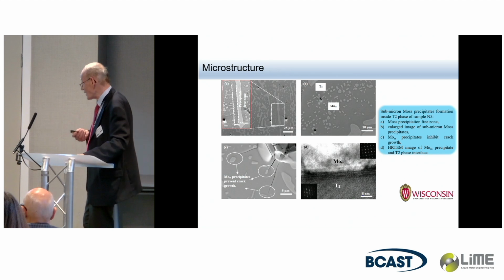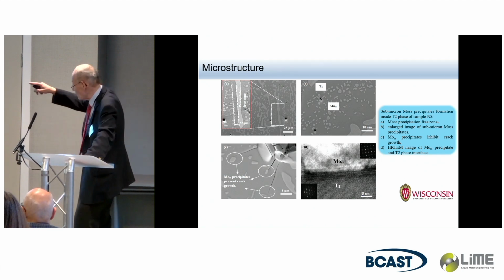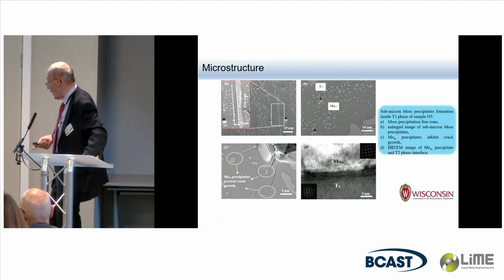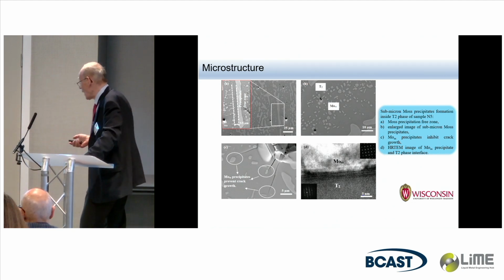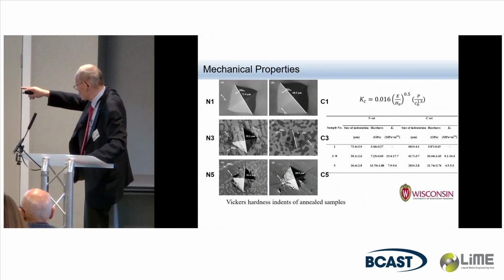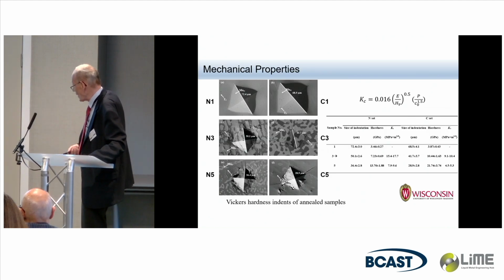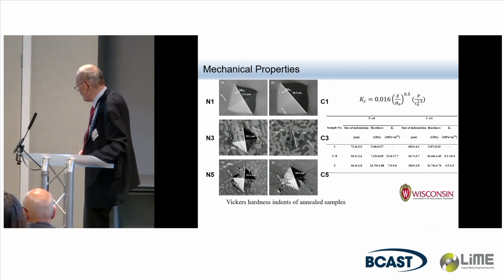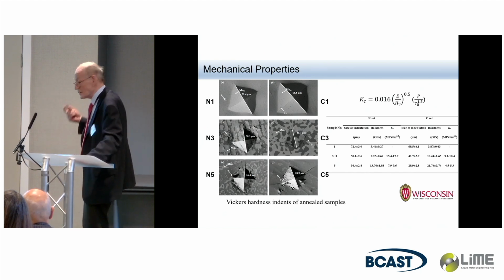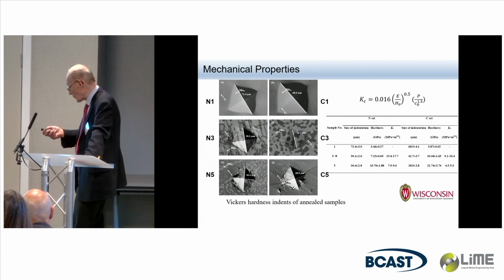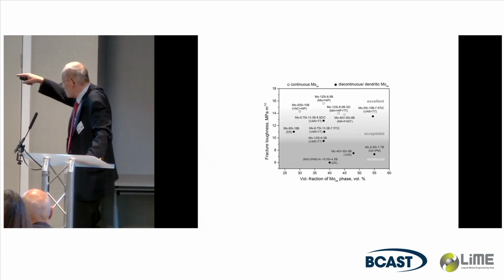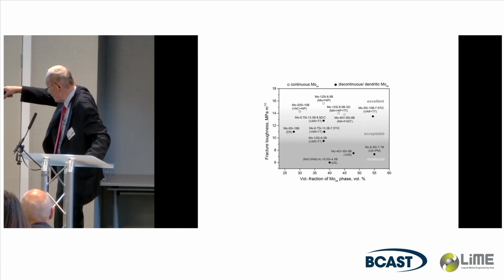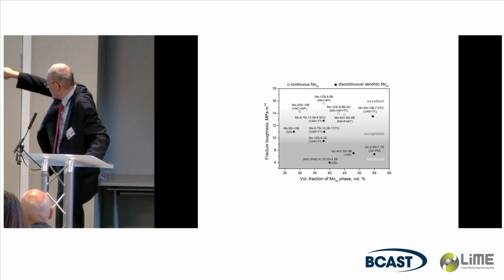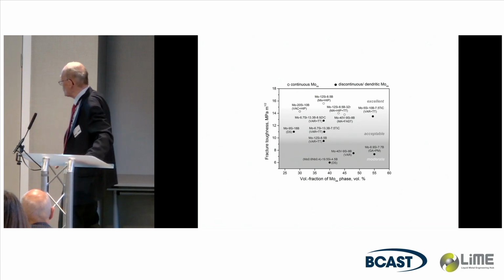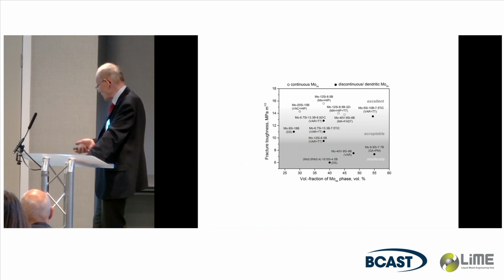So instead of precipitation hardening, we get precipitation toughening. So the molybdenum precipitates in the T2 phase arrest crack growth. And as a result, our toughness went up based on crack formation. So it's around 15 to 17 MPa root meters versus 9 on the other side of the phase diagram. And that puts us in the range where we had about 50% molybdenum solid solution. So the toughness is up with the best alloys that have been produced by powder metallurgy.